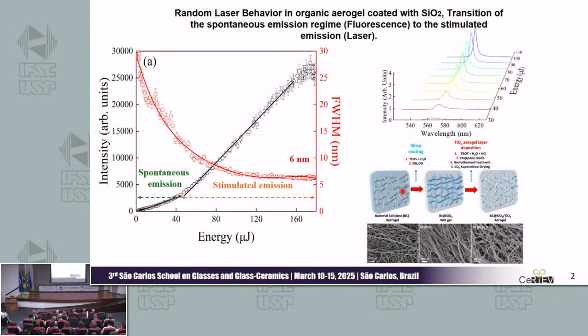So the bacteria create this cellulose, and we did a coating with silica to protect the nanofibers from the degradation of titanium oxide. And we did the titanium oxide deposition to act as scattering centers. And after that, we put rhodamine 6G to act as a gain medium.